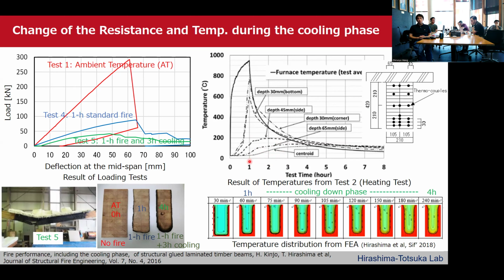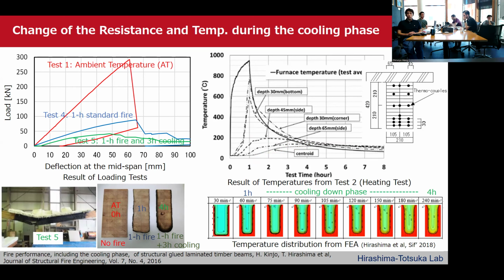But then the temperature rose, reaching 100 degrees after 4 hours. In order to understand the resistance during the cooling phase, it's necessary to predict the internal temperature distribution and then properly assign the mechanical property of wood according to those temperatures.